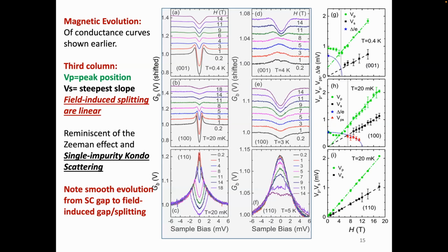In any case, whether you're looking at the green curve or the black curve, that splitting grows linear with applied magnetic field. And what you see in the red and the other thing is sort of the gap. So what we do is we fit to a couple things. We fit to BTK, and we also find this linear growing with applied magnetic field. Very interesting. What does linear mean to me? Well, I've been doing this a long time, and linear says every 1, 2, 3, Zeeman splitting.